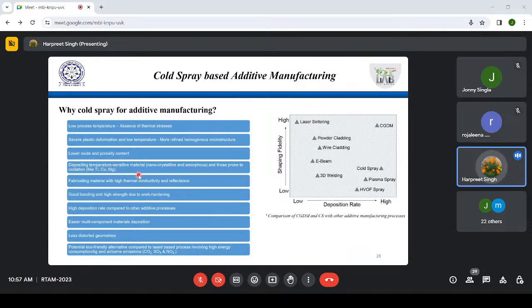Depositing temperature sensitive materials, nanocrystalline materials, and those prone to oxidation, all these materials can be deposited by cold spray. What is the limitation then? The limitation is that very fine powders cannot be used. Let me tell you, you think about cold spray right now only when the particle size is from say 20 to anything up to 100 micron or something of that sort. If it is less than 20 micron, it becomes very challenging. Although we have done it for 10 micron also, maybe those particles were good enough, but I will prefer 20 micron upwards.